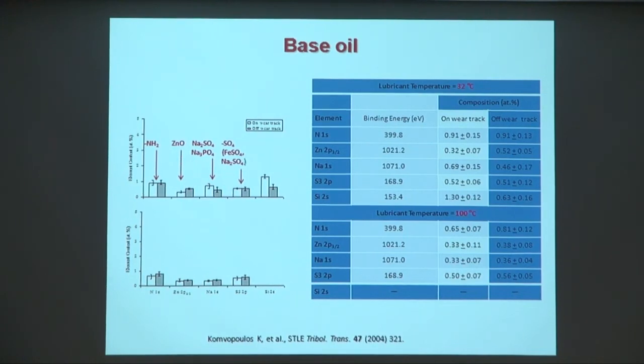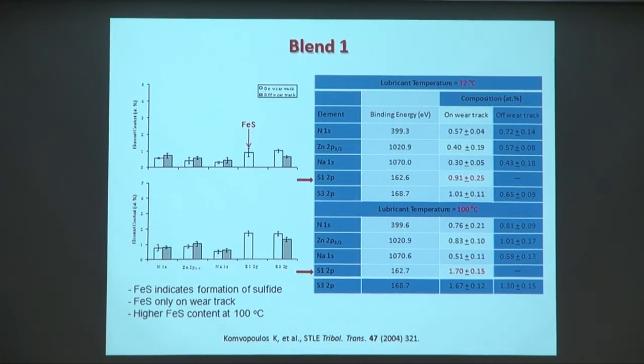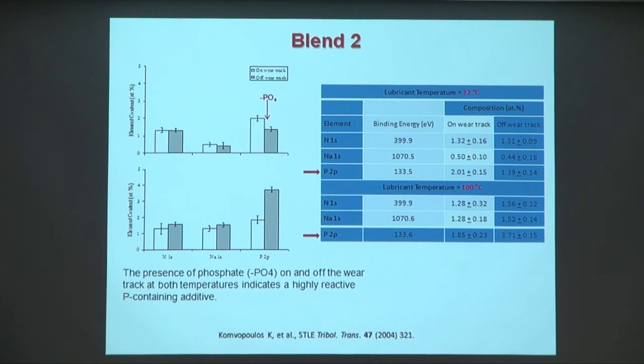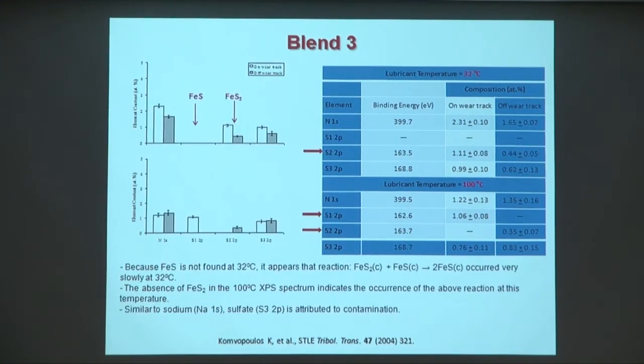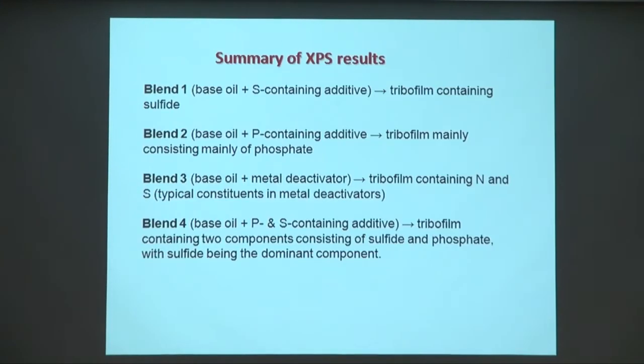I will skip the chemistry. This is XPS that shows the composition of the films in order to go to the summary of this. So what we can say about these gear oils, that the first blend that had the base oil and the sulfur-containing additives had a tribofilm formation that was sulfide but was not protective.